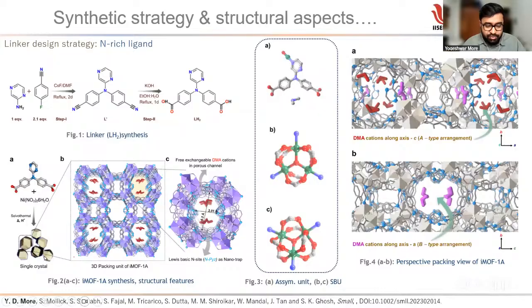To get this MOF, we had to do several trials and errors, and we finally got these crystals. The 3D packing unit of the crystals is shown here, which has the geometry and the DMA cations inside. So why does it have DMA cations inside? The reason being the crystal is anionic overall, and dimethylammonium is a cation. So one asymmetric unit generally has nearly two DMA cations. It means twice the positive charge is present, replaceable positive charge within this crystalline framework per unit cell. So that is the beauty of this framework.